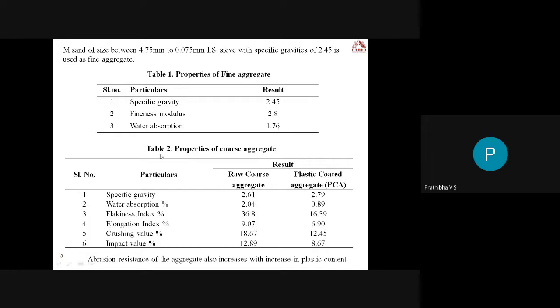Table 2 shows the properties of coarse aggregate, both the raw aggregate and the plastic coated aggregate. Before going to this table, I'll explain the procedure for preparing the plastic coated aggregate. First, we shred the plastic waste to a size of less than 4.75 mm and clean it thoroughly so that all pollutants are removed, and it is heated to a temperature of 140 degrees Celsius. The types of plastic used in this study are polyethylene and polypropylene, which may emit hazardous gases while heating, so the temperature is kept below 150 degrees Celsius.